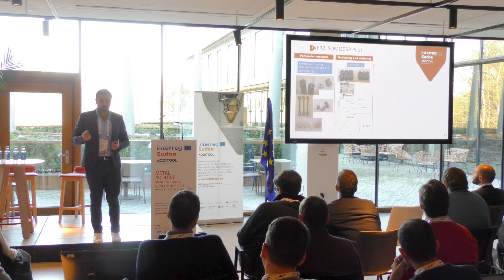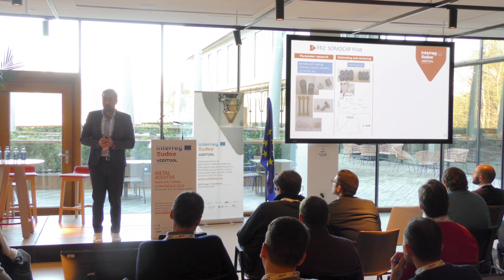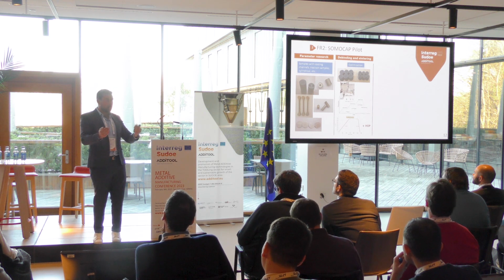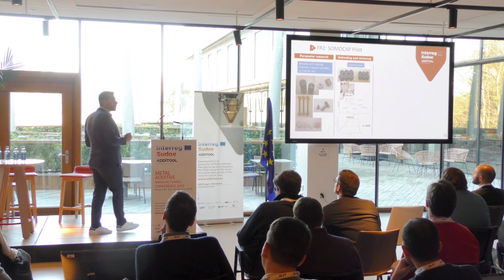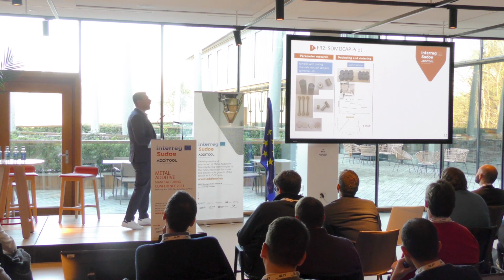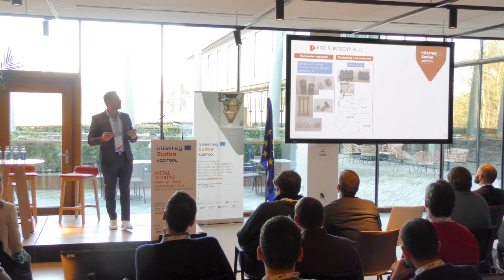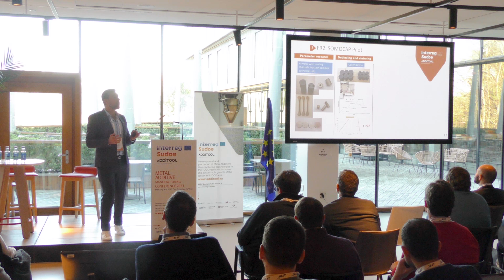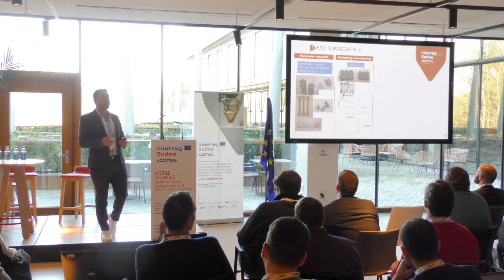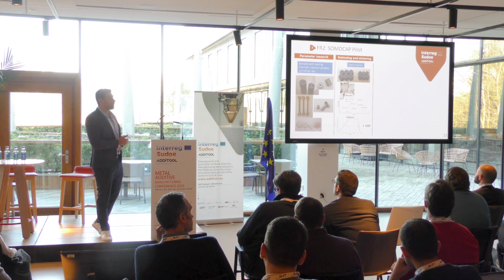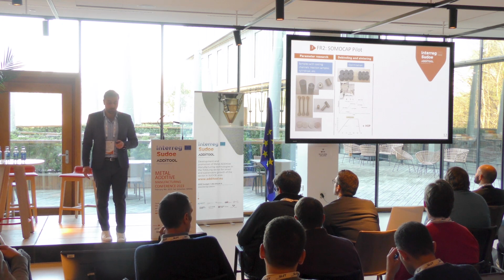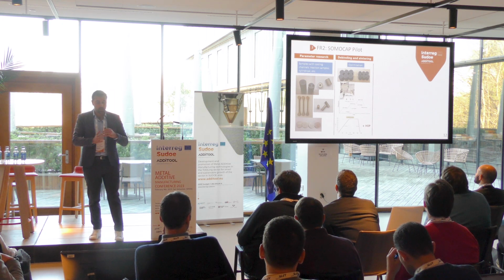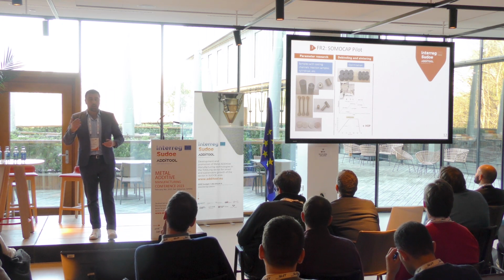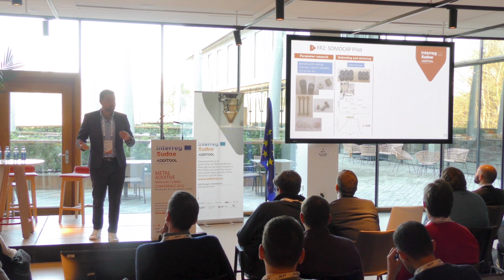So thanks to ENIT, they have performed a very good time reduction on the debinding and sintering, and we have less than 20 hours approximately to debind and sinter. So you can launch a piece on Monday, and on Tuesday you have it. They have optimized all the value chain, performing some HIP, hot isostatic pressing, etc. on it.